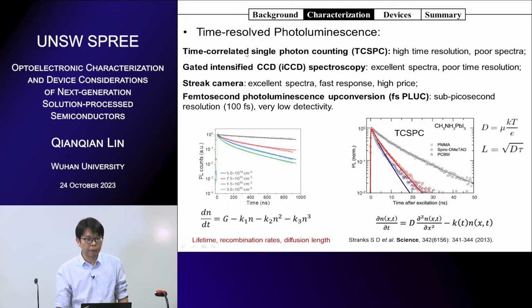Another drawback is that TRPL can be used for most direct bandgap semiconductors because most of them are emissive. Indirect bandgap materials like silicon, or some highly doped semiconductors, have high trap density. These materials are not so emissive and you cannot easily get a TRPL signal. This is the drawback of this technique. That's why we want to develop new methods to look at charge carrier dynamics. Here I want to introduce the time-resolved microwave conductivity measurement, which we can call TRMC.